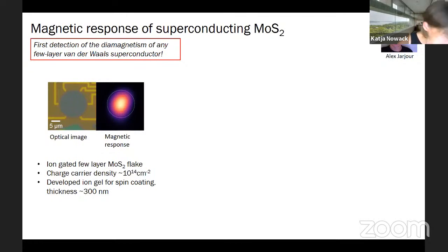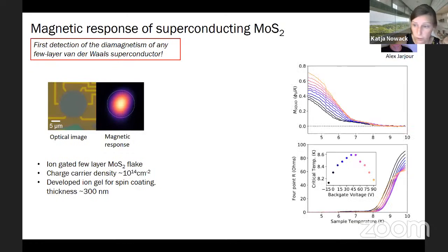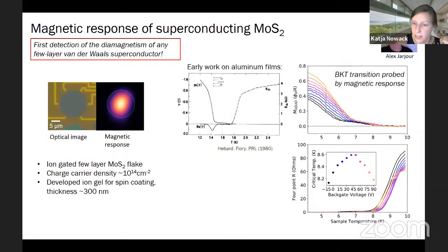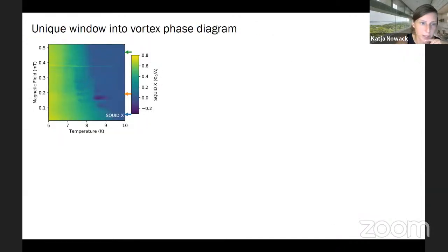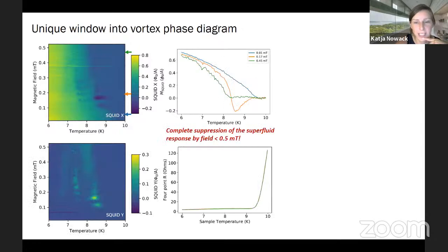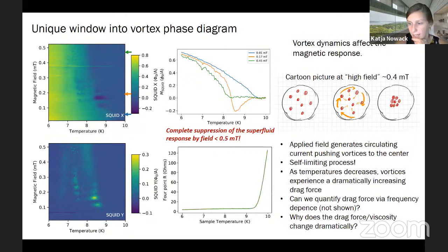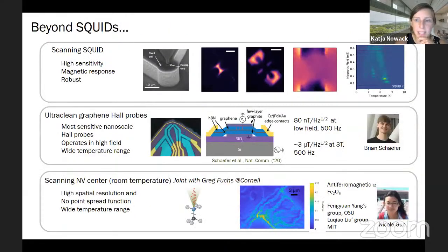What we really want to do is just park our SQUID on top of this device and look at the magnetic response as a function of temperature and also magnetic field. And so we've done that. We think we see some signatures of the BKT transition in these superconductors. And then we also see interesting features when we turn on the magnetic field that we think are associated with interesting vortex dynamics. I will stop here.